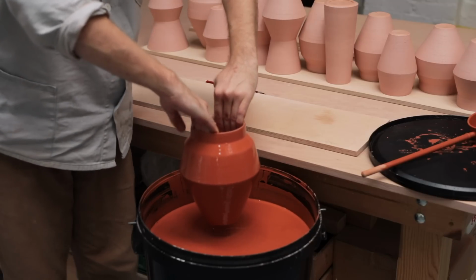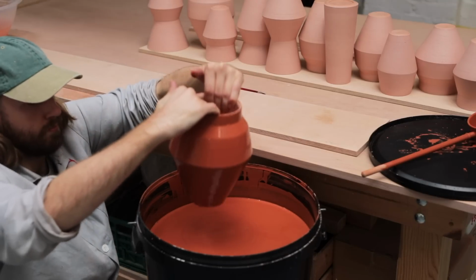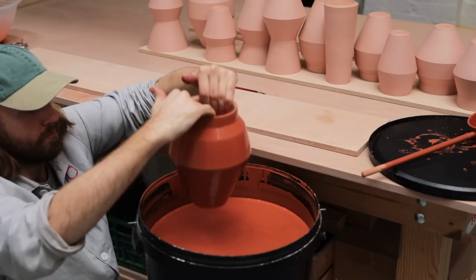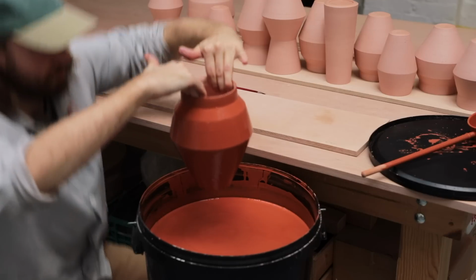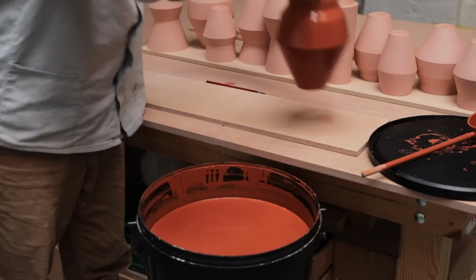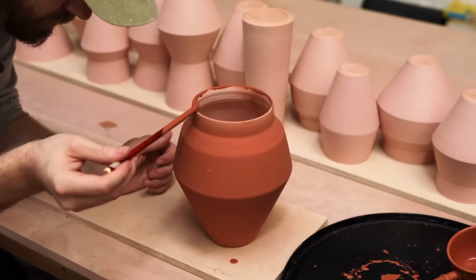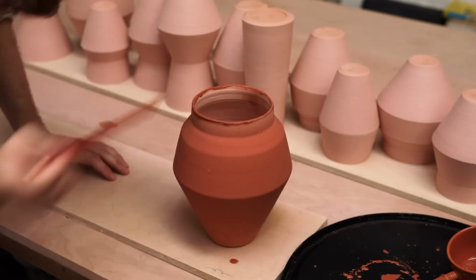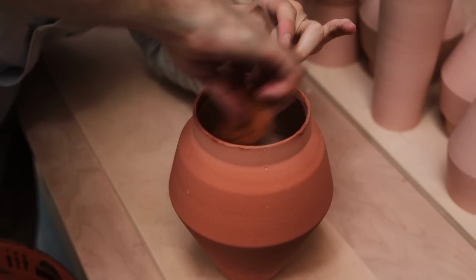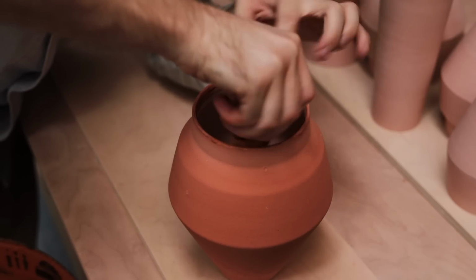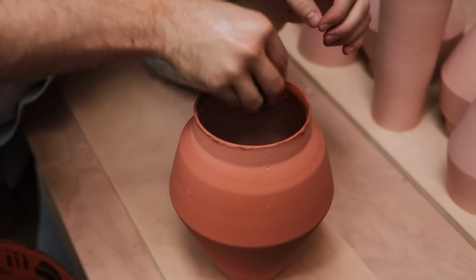For many of my pots, I glaze the outside first and then the inside. That's just my particular way of doing it for this particular recipe. It's what has given me the best results, as by glazing like this I can get very clean, flush surfaces on the outside. Although in this case I didn't glaze it quite high enough, so I had to brush on some more glaze and clean up the interior portion of the rim thereafter.